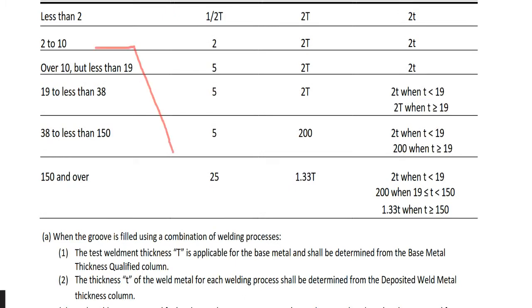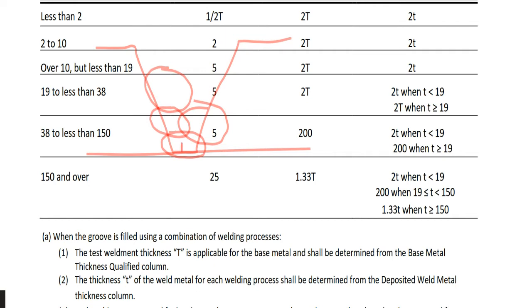We have a groove weld, and first pass, root pass, and second pass, third pass, fourth pass, and this is pass number 1, 2, 3, 4, 5. And the thickness of this single pass is greater than 13 millimeter. So let's say this is 15 millimeter.